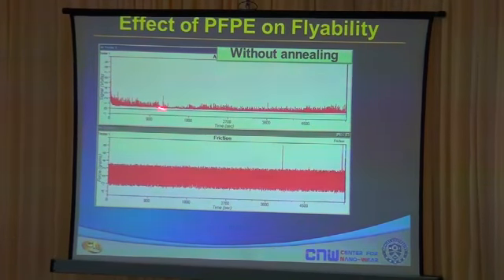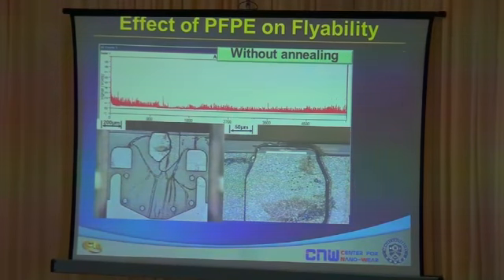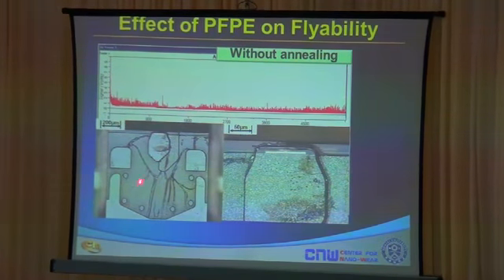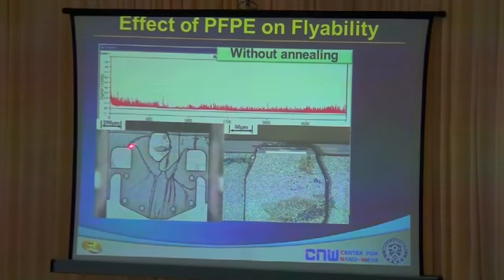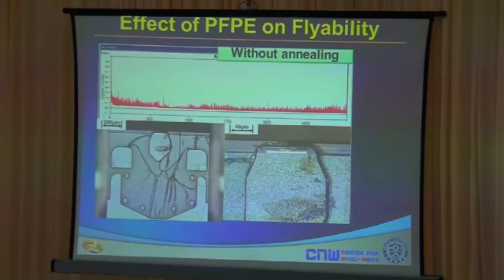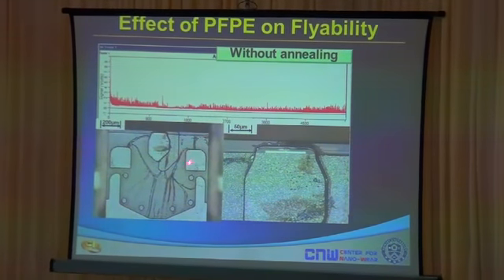Now, this is the effect of PFPE on flyability without annealing. This is the acoustic emission signal, and this is the friction signal. You can see that there's quite a bit of noise in the signal. And after you do this test, we disassemble these parts, and we look at the slider face, and you can see that the slider face is contaminated with lubricant. These are all patterns on the slider that allow the slider to fly at a certain height. But you see streaks of lines which are contaminations from the lubricant on the disc.